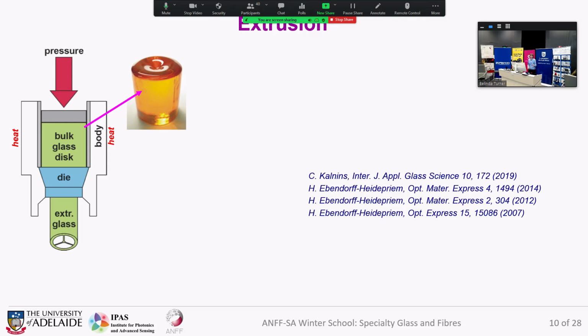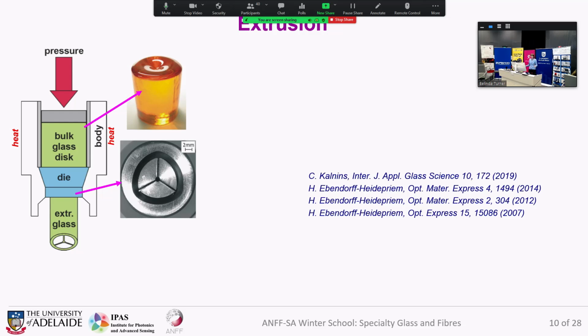We either buy or make our own in-house glass billet. This billet is placed on a so-called extrusion die, mostly made out of metals, and you see here the die exit structure, which then determines the structure of the preform.